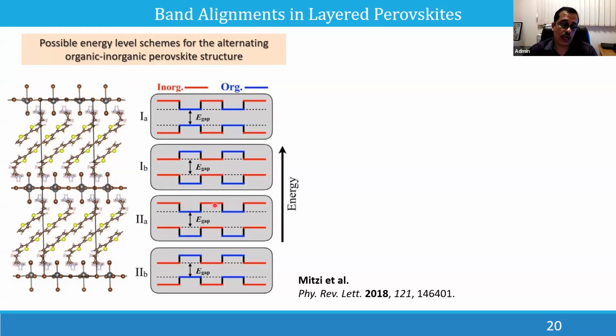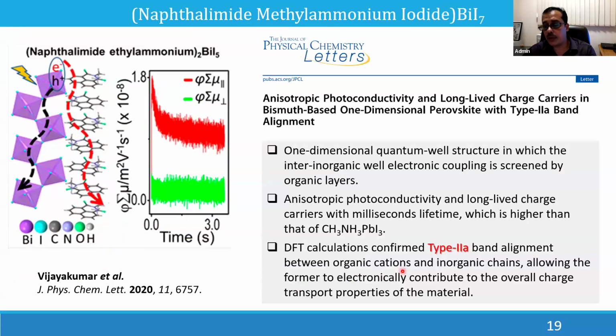So the organic component is giving the conduction band minimum. That part is decided by the organic component. And if it is reverse, like valence band maximum by the organic component and conduction band minimum by the inorganic component, then it is a type 2B. So in this structure, we got a type 2A.